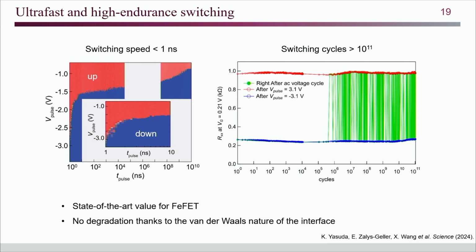Yeah, so to study that, we apply electric pulses to study this ferroelectric switching dynamics. So first, we studied the switching voltage as a function of the switching time. What we do is that we first initialize the polarization to one state, and then we apply a pulse with a negative polarity. And by varying this pulse duration and this pulse magnitude, we examine at which voltage we have this polarization switching. We can see that as the pulse duration gets longer, the voltage we need to switch is getting smaller. This agrees with the typical ferroelectric switching behavior.